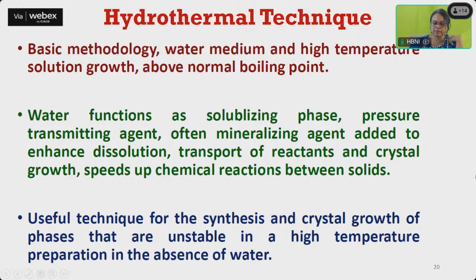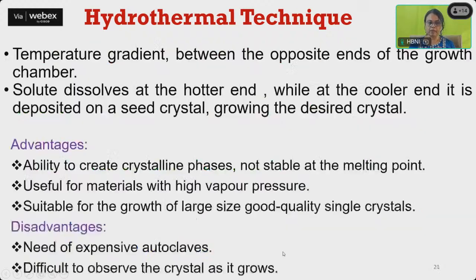And water functions as a solubilizing phase. Pressure transmitting agent. Often mineralizing agents are added to enhance the dissolution, transport of the reactants, and crystal growth, and to speed up chemical reaction between the solids. So it is a useful technique for the synthesis and crystal growth of phases that are unstable in a high temperature preparation in the absence of water. We have a temperature gradient between the opposite ends of the growth chamber. The solute is dissolved at the hot end, while at the cooler end it is deposited on a seed crystal. Very similar to what we have seen earlier, the temperature gradient part, but here we are also applying pressure.